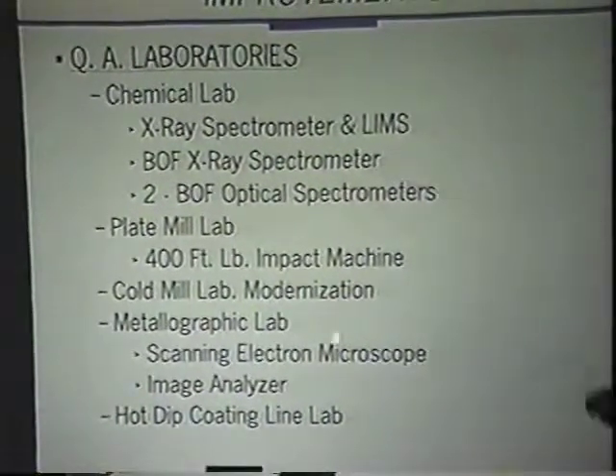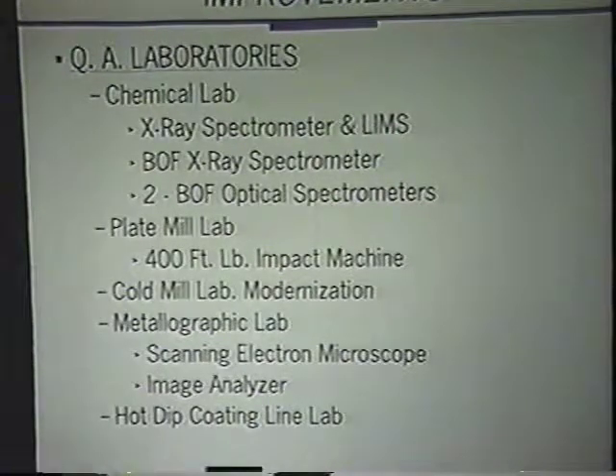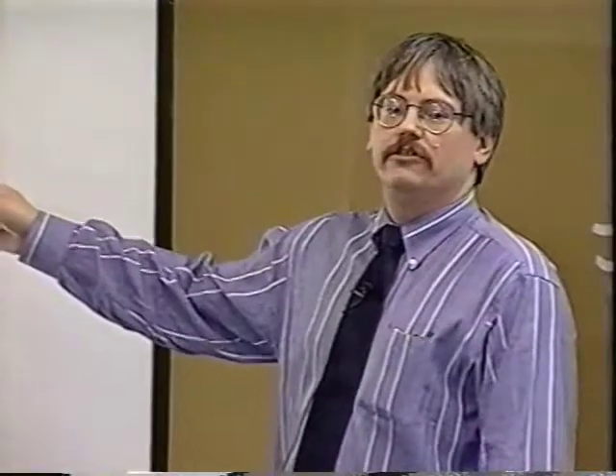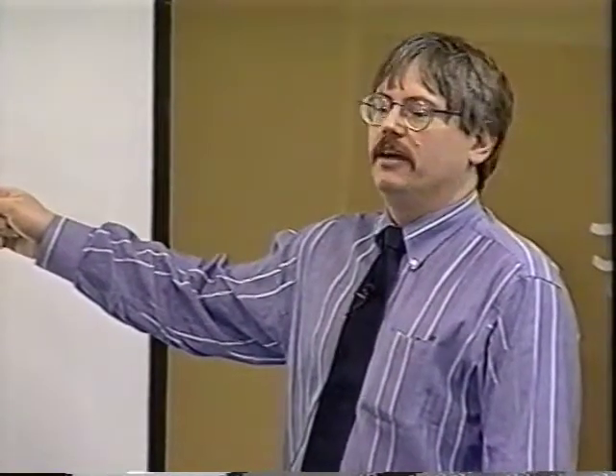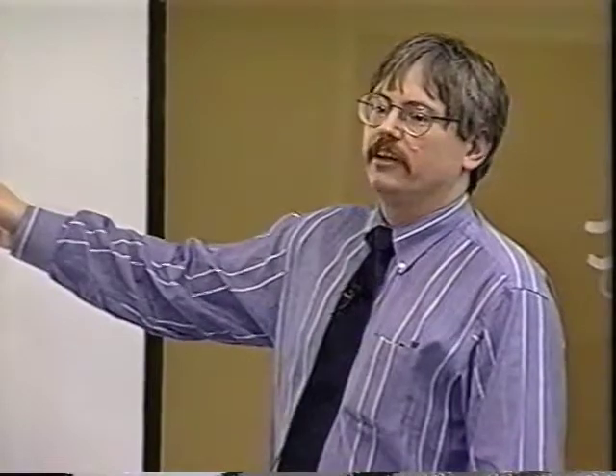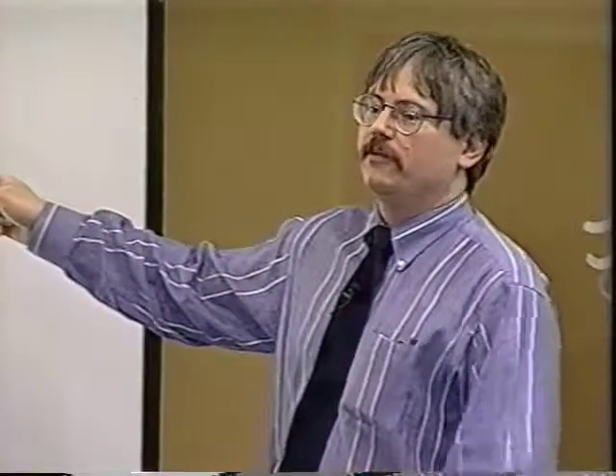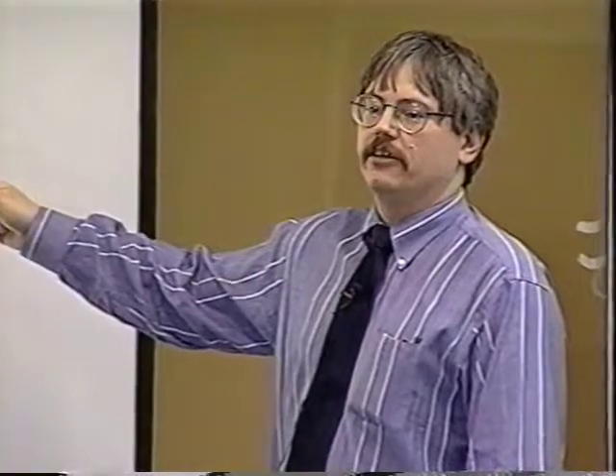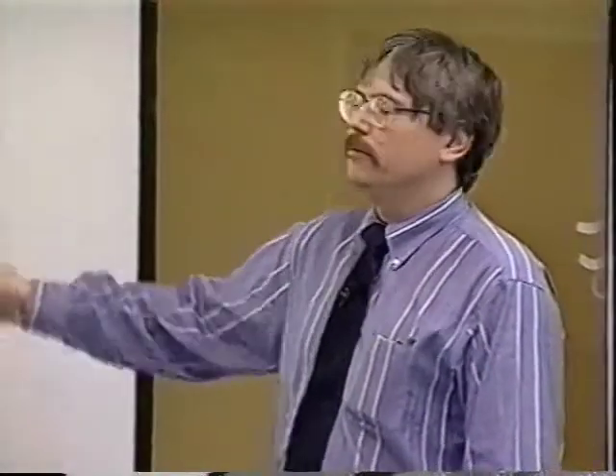This X-ray spectrometer we have in our BOF was essentially done for our interstitial free product. One of the variables we found that was extremely critical for quality on the interstitial free product is to control the percent FeO in our slag. And you think, well, what does that matter? You're making steel, but controlling your slag chemistry really affects the quality of the final product. So what we had to do is put a new X-ray in, test the slag, actually get slag samples off the ladle, test it, and then modify the slag to get our FeO levels extremely low, and that dramatically improved our quality of the final product.